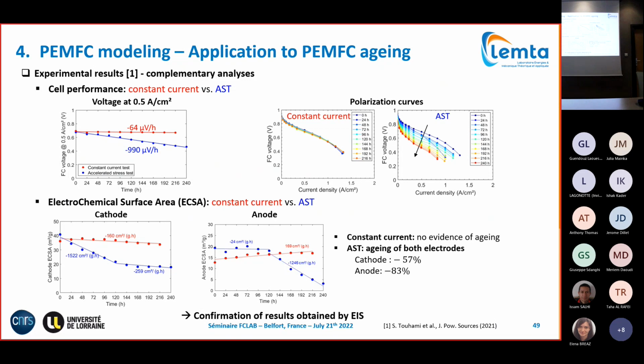Here you see what we obtained, the evolution of the electrochemical surface area at the cathode and the anode. It is an indicator for the state of health of your electrodes. If the electrochemical surface area goes down, it means you lose active sites, which can be carbon corrosion or platinum dissolution. What we see is that at the cathode, the decrease during the AST was logical because we did voltage cycling. Voltage cycling means you subject your cathode to corrosion. So this is in agreement with what we observed in the literature.